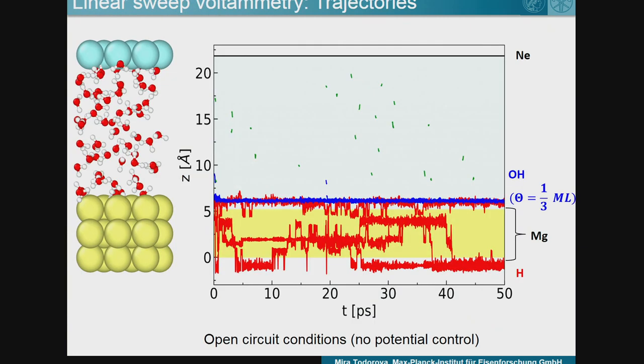So these are some details of the setup. And first, we did just a calculation without applying any voltage. What is left here are the trajectories of some of the interesting atoms. Water molecule trajectories are blended out, and also the magnesium trajectories that are not interesting. But what you can see here is that almost immediately we have the dissociation of water and forming of OH groups and hydrogen groups. And for the time of our trajectories, we ended up with a coverage of one-third monolayer of hydrogen and OH on the surface, which is also consistent with DFT calculations and other calculations which just look at ground state properties.